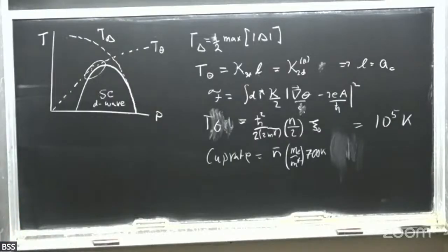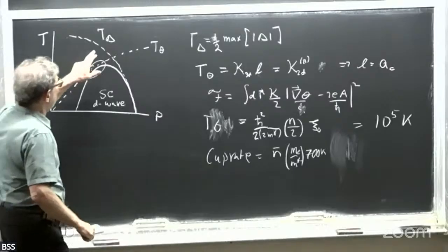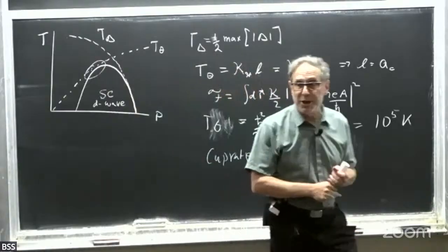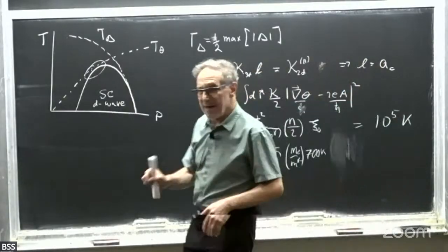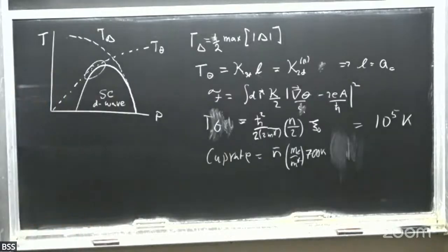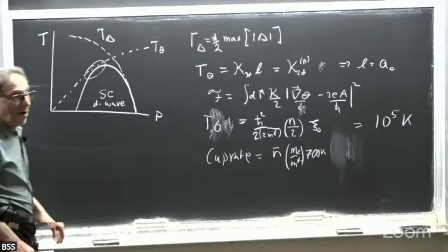When you say pairing is stronger, that's the pseudogap that you're referring to, or? So, no. Remember what the strategy here is. We're using zero temperature data to predict Tc. So this is a measurement of the gap at zero temperature. Now, it's supposed to be a measure of the superconducting gap at zero temperature. And at the time, there were gaps, but we, of course, didn't know how to distinguish the measured gaps from the superconducting gaps. So fortunately, we do now.